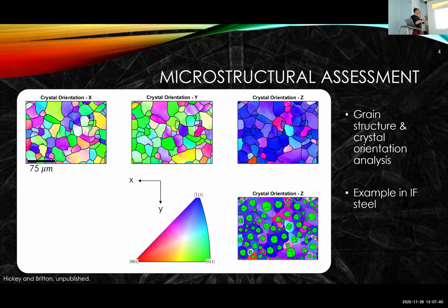In this material system, it's a body-centered cubic metal. We have effectively an ensemble of different grains, and I'll discuss briefly the different color coding. For those of you who are less familiar with the color coding, we're measuring at every single point in this map the orientation of the unit cube. The fact that it is very blue in this map tells me that the 111 crystal direction is pointing along the z-axis. So the points of the cubes are pointing out of the plane of the page. And for instance, things like the stiffness of the system can vary by 30% based upon the crystal orientation, just due to the change in bonding in that material.